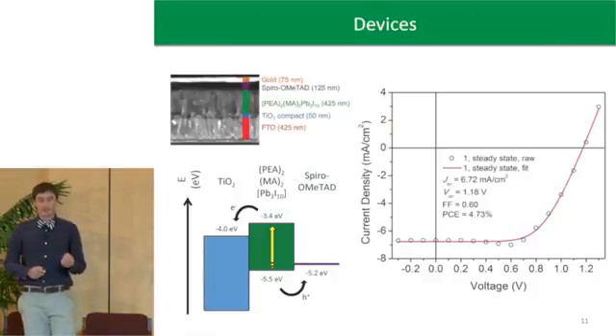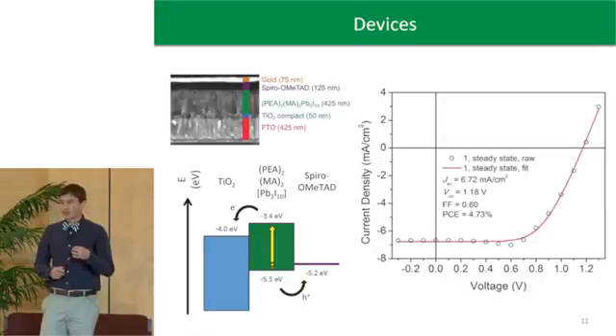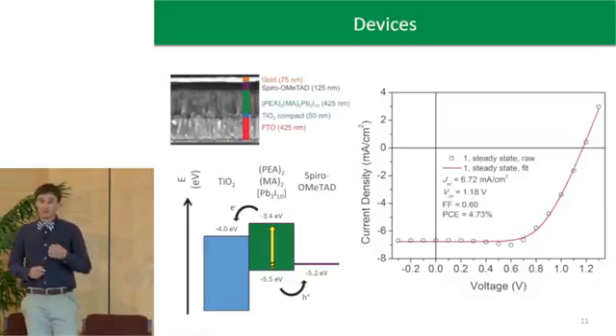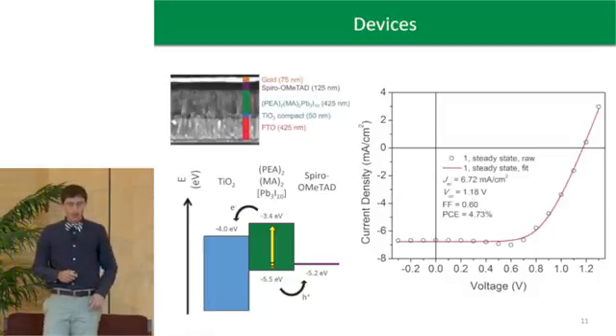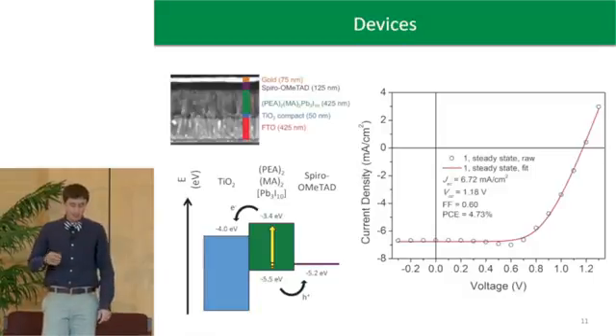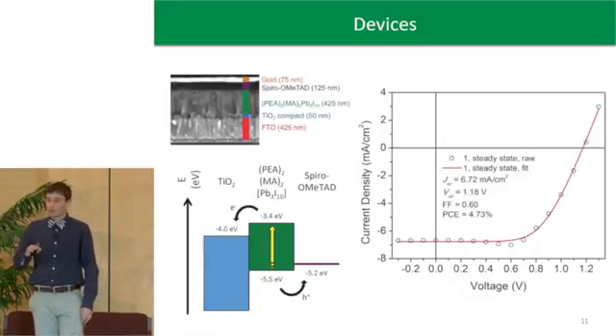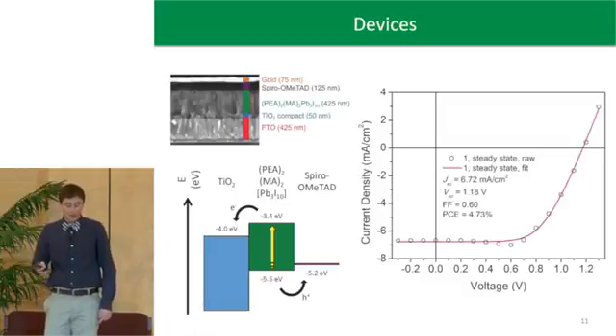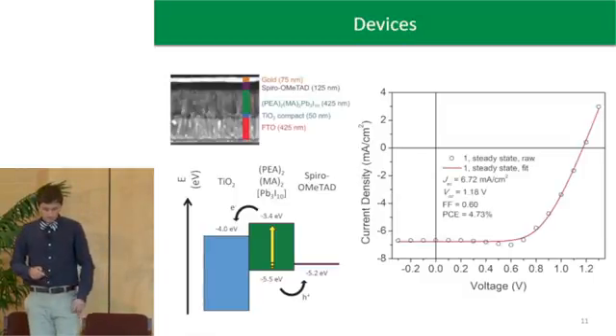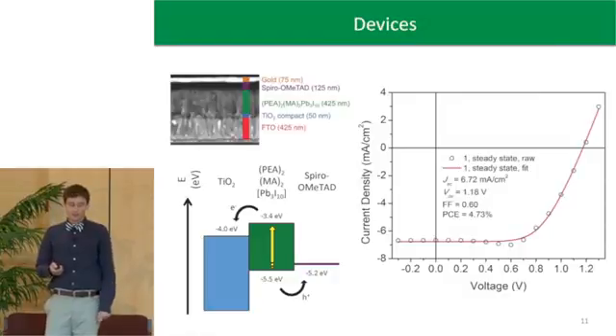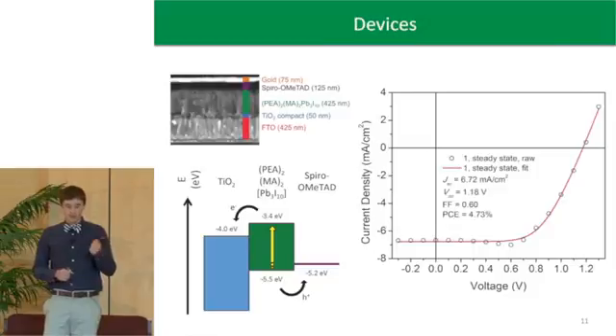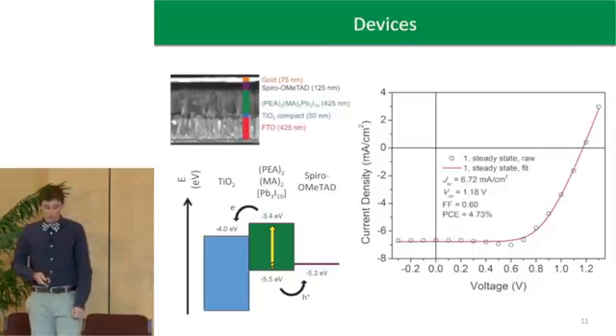And finally, I was able to make devices. This is essentially copying what's done by some people in the literature. It's a titania compact layer, which is your N-type material, followed by the perovskite, your hole conductor, which is an organic polymer, Spiro-OMeTAD, and then gold. Light goes into the layer of the perovskite, you get your hole and electron pair, and then you extract those into the titania for the electron and the Spiro-OMeTAD for the hole.